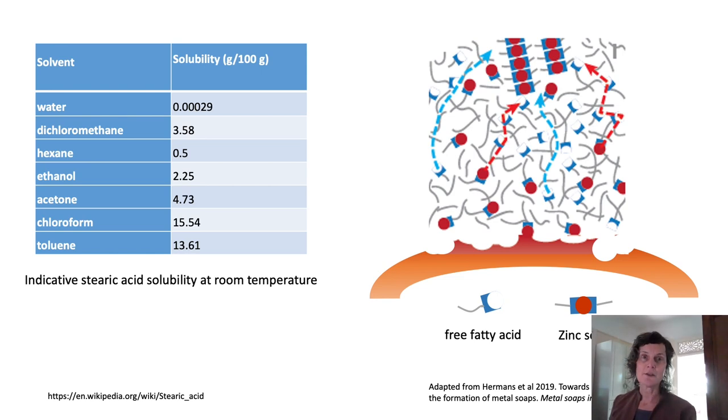While essentially insoluble in water, stearic and palmitic acids are considered soluble in the range of solvents likely to be encountered in conservation treatments. Solvent choice and the amount and duration of exposure have been shown to influence diffusion. Together with paint condition and the degree of oil polymerization, these factors will determine the extent to which fatty acids are mobilized by solvent exposure.